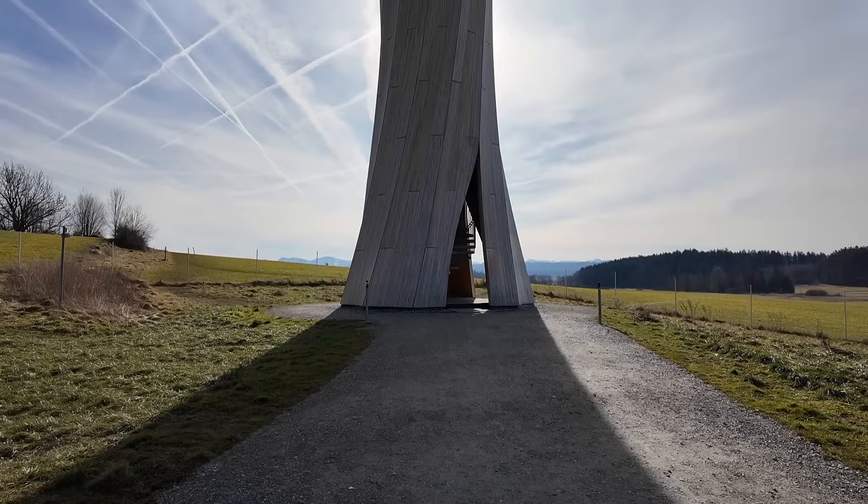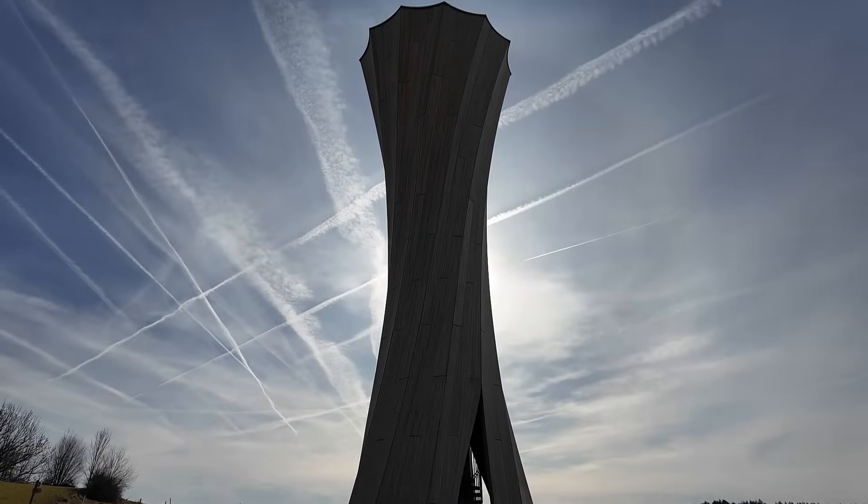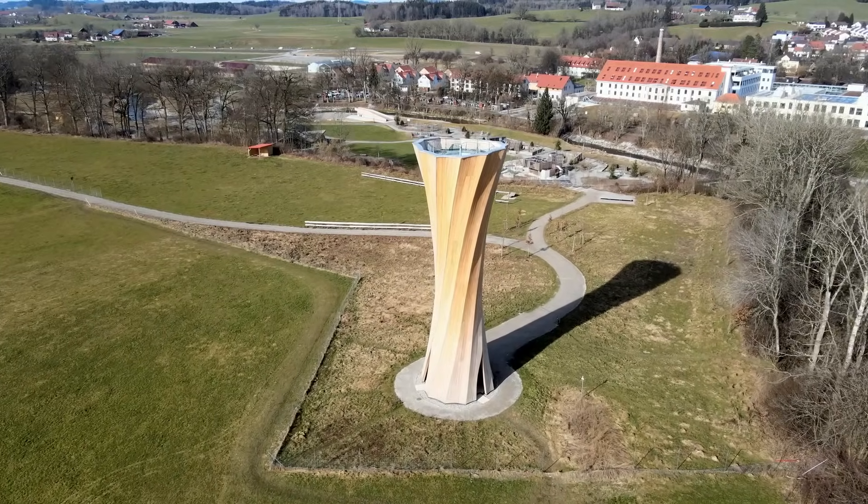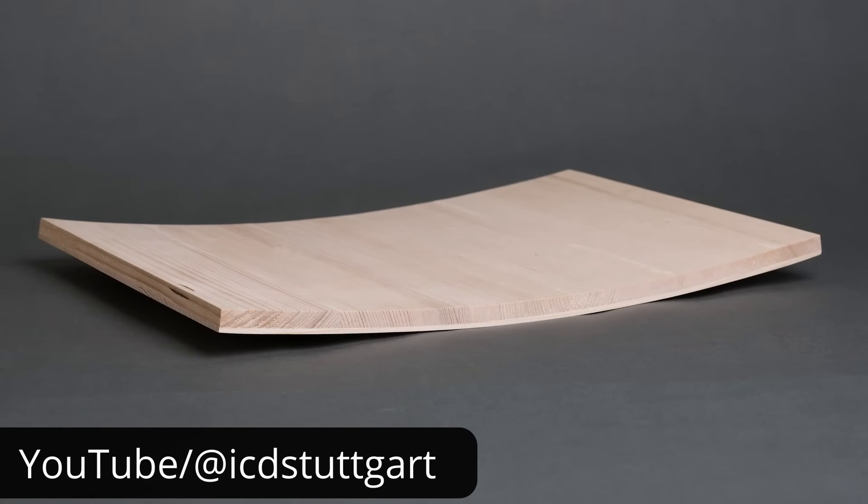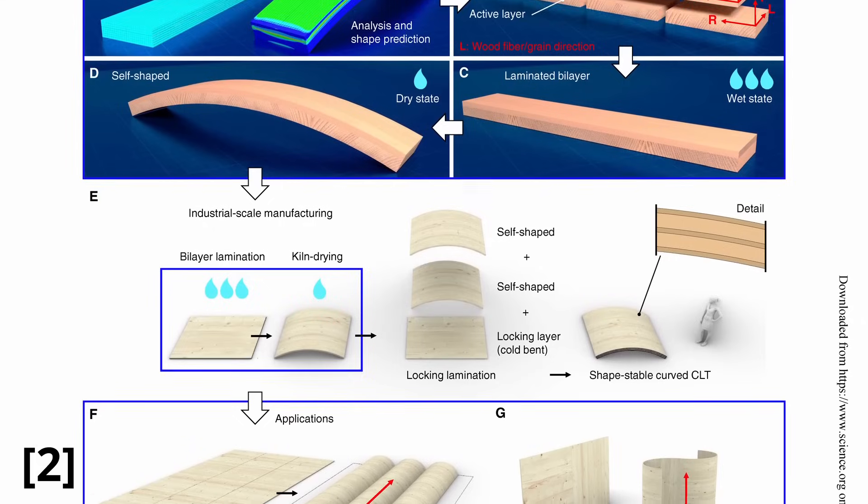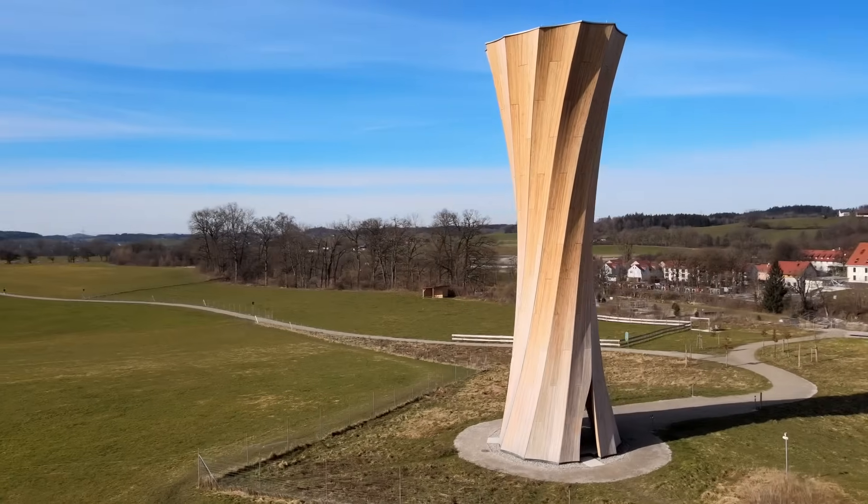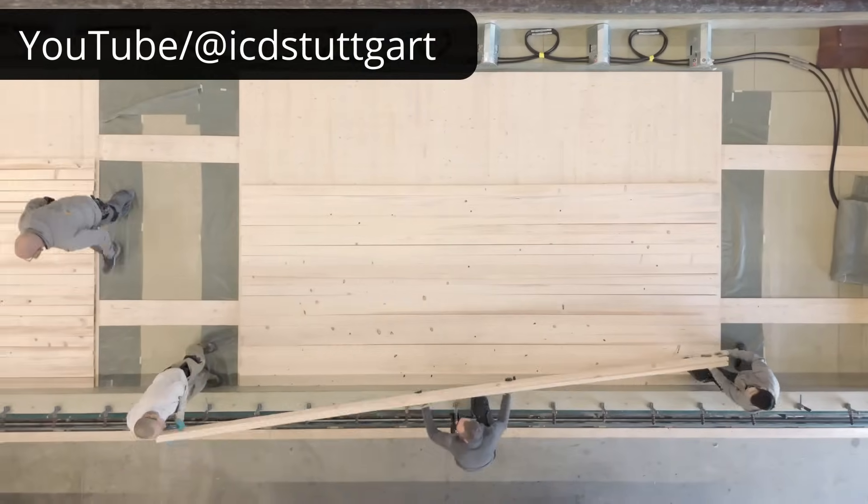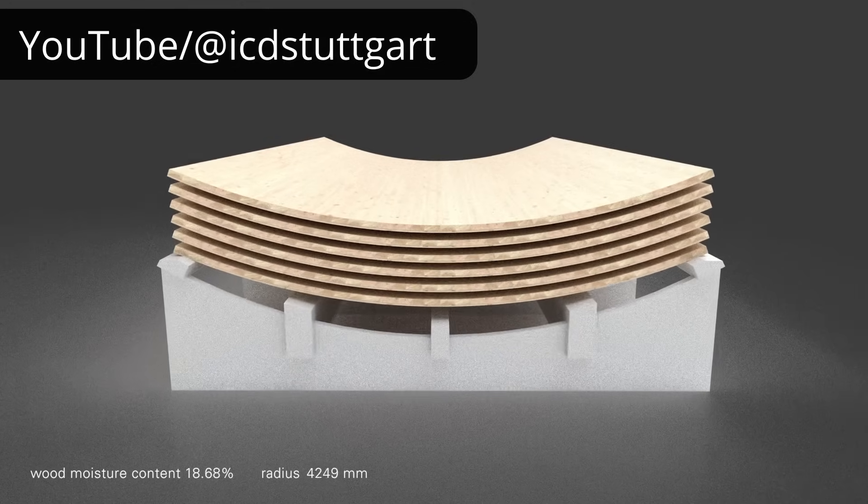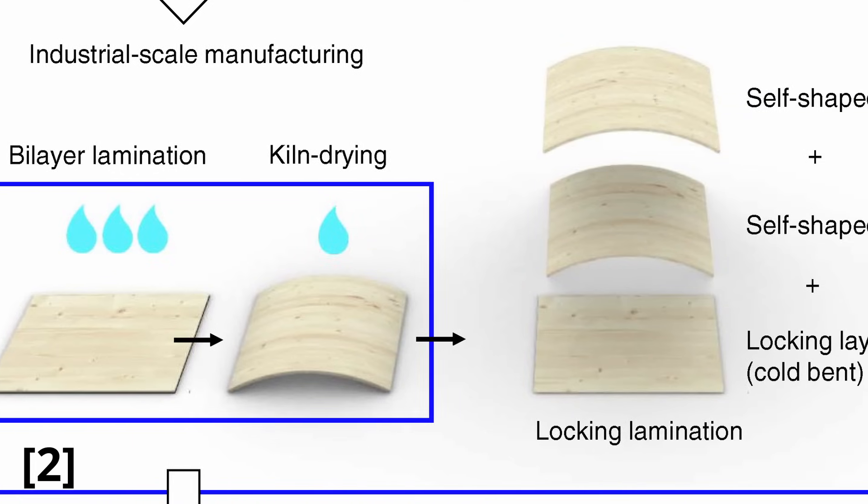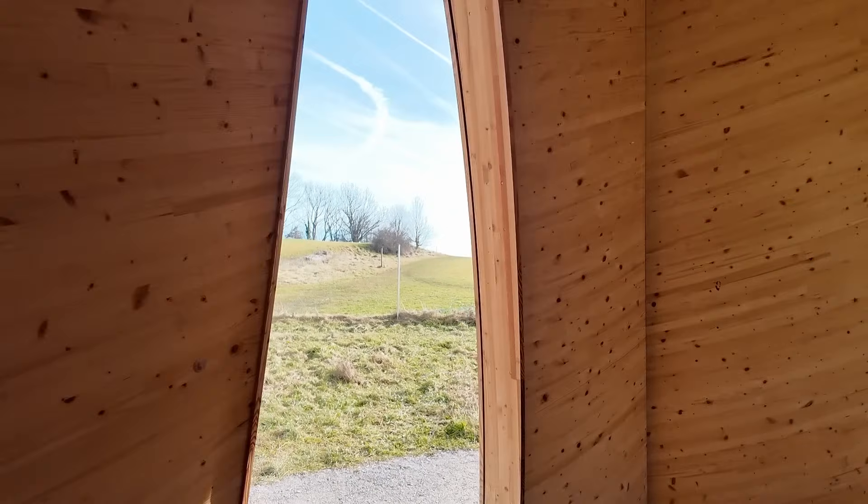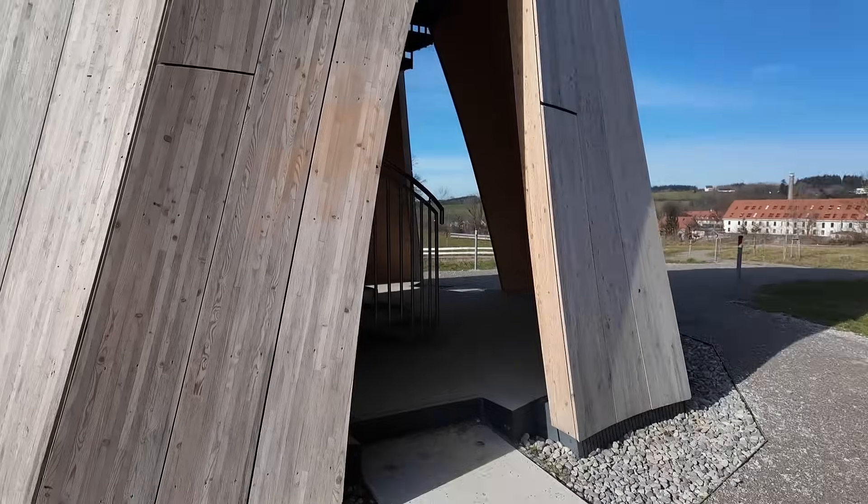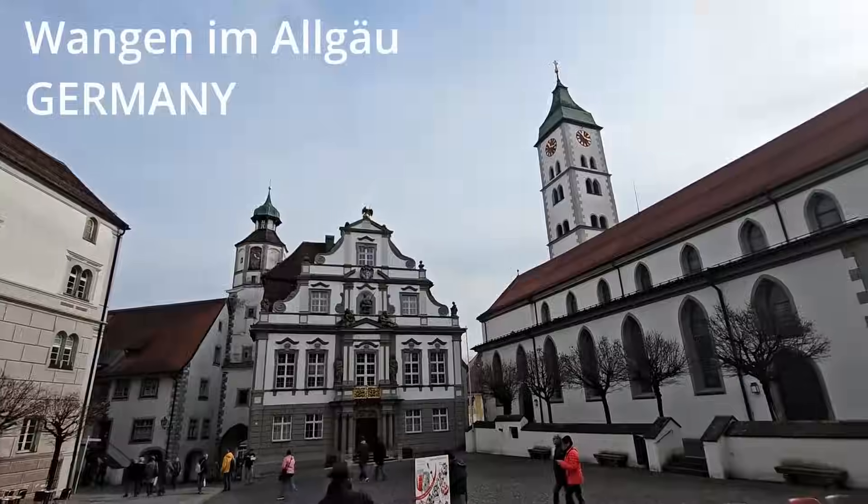Real-world applications of self-folding structures aren't actually too far-fetched and there's a massive building in my city that has been built with a very similar technique. This is Wangen Tower, a unique wooden lookout tower built just a year ago for a huge garden expo held here. Just like our Thermorph structures that deform under the internal stresses induced during 3D printing, the large and thick plates used to construct this tower were also shaped using a morphing technique. But instead of activating the deformation by temperature, these wooden panels were morphed after gluing them together while they were still wet and then drying them out. Wood shrinks differently during drying depending on its fiber orientation. By stacking the wood sheets in different orientations, they were able to create impressive three-dimensional structures without needing large presses or extensive machining. Once the panels were dry, a locking lamination was applied to prevent them from unwarping due to changes in humidity. I'm really grateful to have such an impressive structure right where I live that employs very similar morphing techniques we also explored in this video. If you're ever in southern Germany, be sure to check out this tower as well as our city.